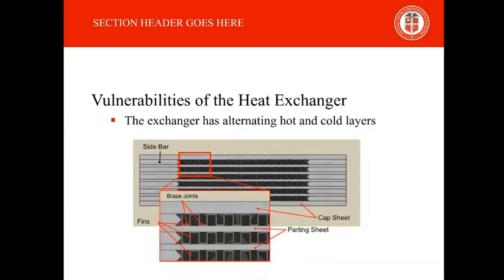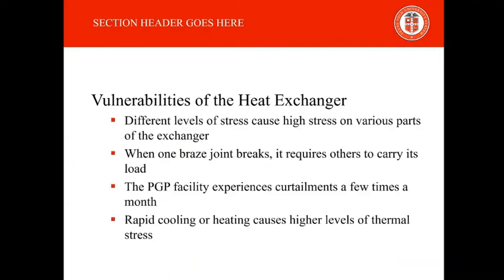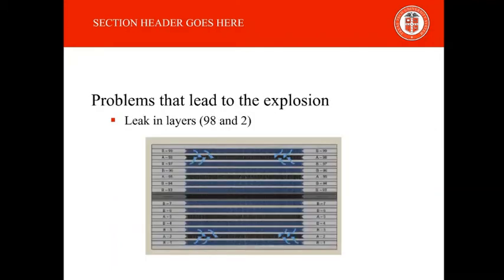When a BAHX is exposed to fluctuating thermal stresses over an extended period of time, this can lead to thermal fatigue, which will be one of the main causes of this accident. The post-incident examination of this exchanger revealed very clear service-related thermal fatigue at several locations. The exchanger was already experiencing thermal fatigue in September 2015.